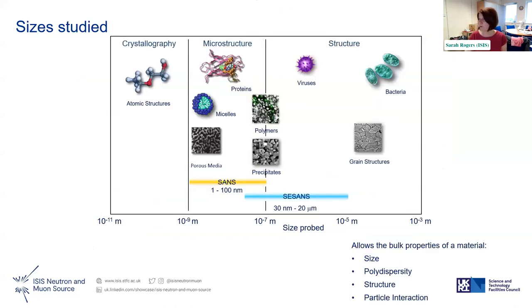So just to give an overview of what the size is and what we can look at. Obviously you have your crystallography on one end, which is classical diffraction. The microstructure is in the middle, which is where SANS sits. We tend to look at proteins, micelles, polymers, porous material, precipitates, etc. So a few nanometers to hundreds of nanometers. And then SESANS really kicks in, where we can start to look at viruses, some grain structures, that kind of thing. But that's the overlap between the classical diffraction, SANS and spin echo SANS. So we cover quite a broad range at ISIS. And typically we look at bulk properties, so structure, size, polydispersity, particle interaction, that kind of thing.